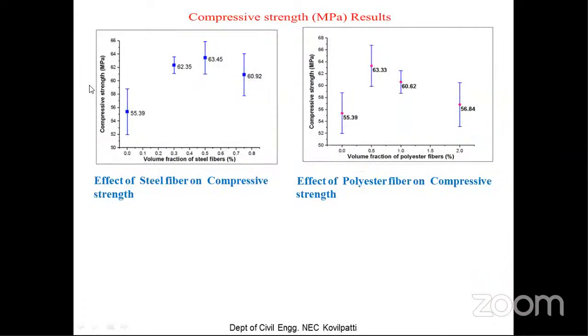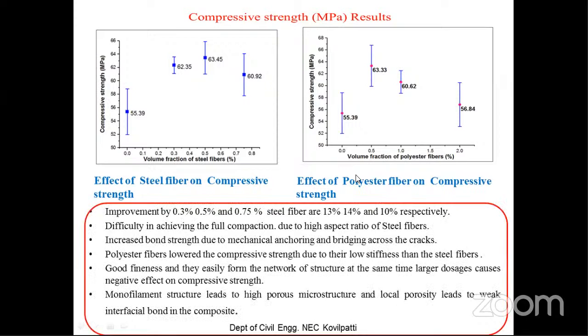So I have analyzed the influence of fibers in the single fiber FRC: the effect of steel fiber on compressive strength, and the effect of polyester fiber on compressive strength. You can see that with polyester fiber the compressive strength is lowered because of the low stiffness, which is an already expected property. Whereas with steel fiber it has been improved because it has good mechanical anchorage, and binding across the cracks is also very good.